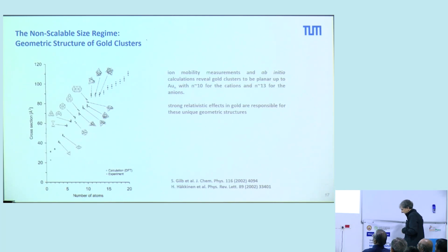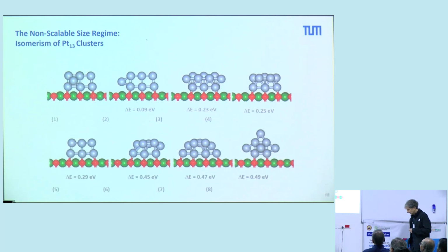But there are other facts which are relevant in these non-scalable size regimes. We have different structures. These are calculations by Uzi Landman, and he observed that gold is planar, nothing to do with bulk. That means this will also influence the catalytic properties. But even more, in these very small clusters, one of the very important properties is that you have different isomers, and they can be very close lying.